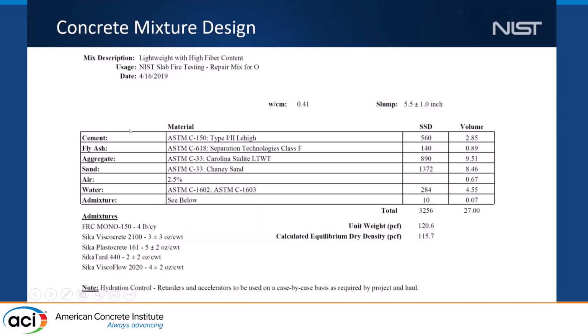So this slide basically shows the concrete mixture design. I believe this is the typical concrete mixture used in the composite floor construction with the lightweight aggregate concrete. In these particular experiments, we actually used the polypropylene fibers, FRC mono 150, just to mitigate the spalling failure that could ruin the fire experiments. But adding this polypropylene fiber is not very typical in common construction.